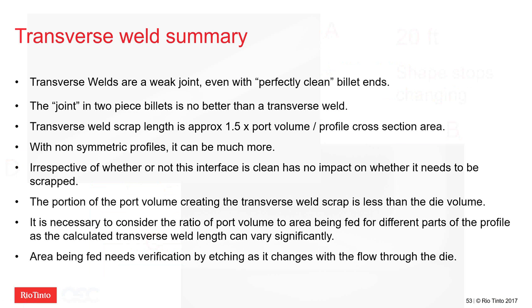So, a lot of words here. Don't worry about all of this. You can read this at your leisure. But look, transverse weld is a weak joint. Not just for the regular process, but also for two-piece billet. So keep that in mind. Again, the scrap length is approximately 1.5 times the port volume over the profile cross-section area. Okay, and with non-symmetric profile, it can be much more.